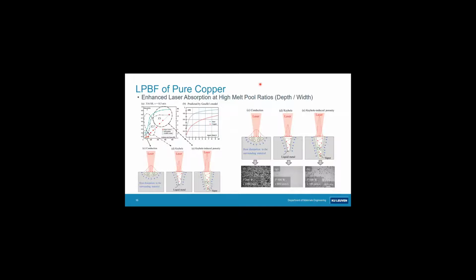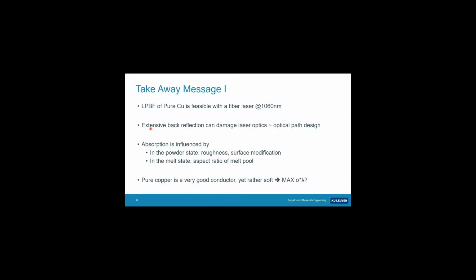So as the aspect ratio of your melt pool increases, so as the depth increases and you evolve towards more keyholing mode, you see a net increase in your absorption behavior. So besides pure intrinsic and extrinsic effects, as your laser beam also shines on the melt pool, the shape of the melt pool also has a very strong influence on your absorption behavior, which is something to bear in mind.